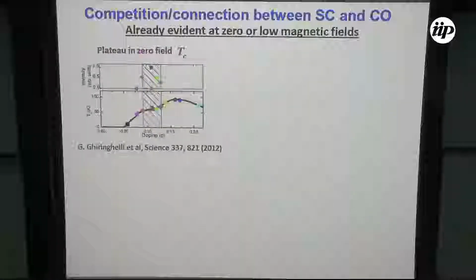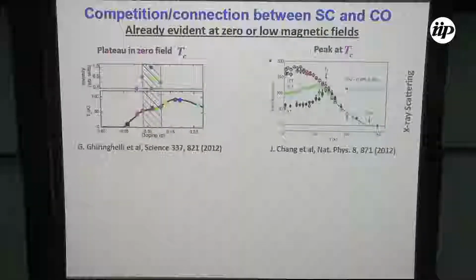If we look at the superconducting transition temperature as a function of doping, we can see that this Tc has a plateau in exactly the same doping region where you see the charge intensity is maximum. If we look at the X-ray scattering intensity for the charge order itself, we can see that it shows a clear peak at T equal to Tc. We see that there is a suppression in that intensity, and this suppression in the intensity reduces if we increase the magnetic field in the sample. For high field, there is no peak at Tc.